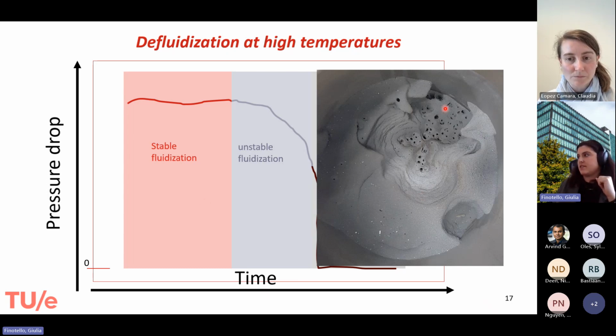So you can see that this is a very bulky, full chunk of the bed that is not moving anymore. And you can see here this part, which are the channels where the hydrogen gas is passing through and is not really mixing the powder anymore. And of course, you don't want such a thing in a really operational condition, because that means that you need to stop your reactor, clean it, and start it again, which in a continuous operation is something that you don't want.